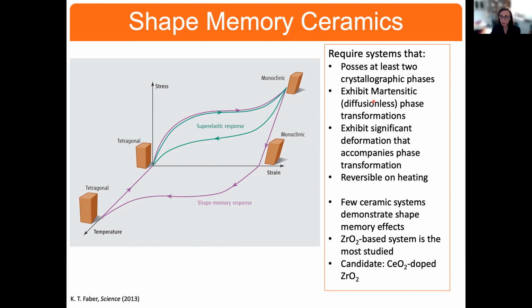The transformation is diffusionless, which means it can keep up with the stress. It's diffusionless, so it's going to be very fast. But it undergoes significant deformation to accommodate that phase transformation. If the material is super elastic, if we unload it, it will go back and change back to tetragonal. If it shows shape memory, we can transform it to monoclinic. We could unload along this monoclinic line, and we get a shape memory response, only to get it back to tetragonal if we heat it up in temperature.